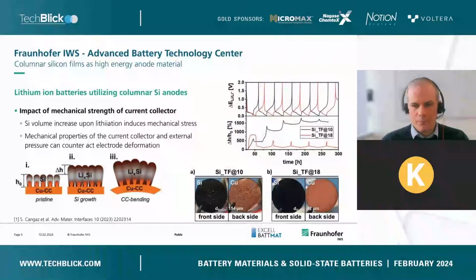effective suppression of the deformation effect in the height measurements upon in operando cell testing. So we monitor the thickness of the cells during cycling, and with the black curve we see a more or less uncontrolled thickness increase. This is due to the deformation effect, which we can avoid in the other case. So we carefully look at this by online monitoring of all our pouch cells.